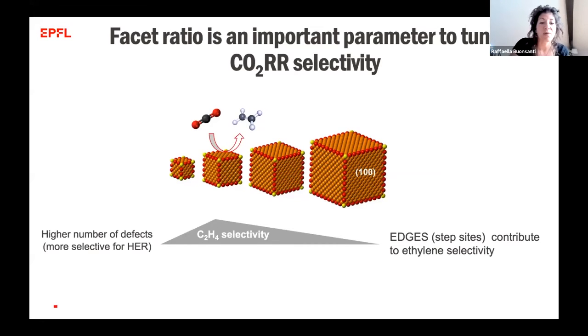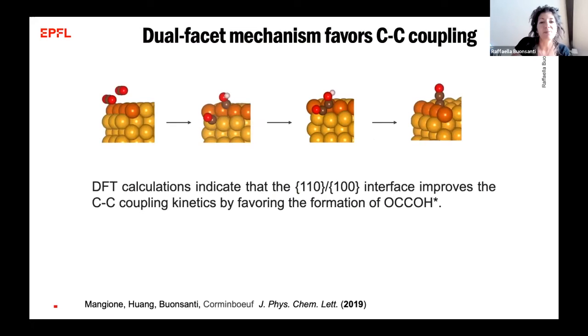But at the same time, we highlight that it is important to have these terraces together with the edges, which are step sites on single crystals, which contribute to selectivity. And the way in which they contribute to selectivity is by favoring C-C coupling. So the 100 facets favor the adsorption of CO, and then these edges favor the C-C coupling, which leads to ethylene formation.